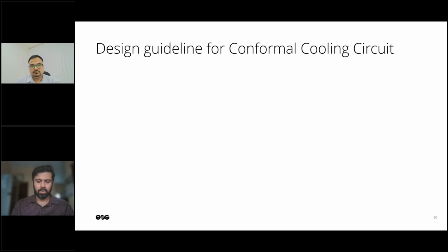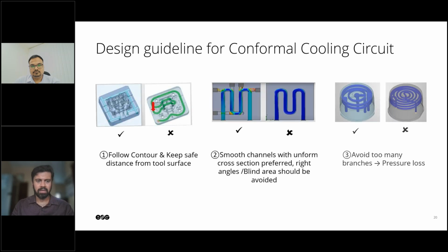So many times people ask us, what are the design guidelines for such conformal cooling circuits? So these are our three primary recommendations. Number one, take the part contour, right? Have an offset from the part contour and keep some distance. There is also a guideline depending on the material. Second is, don't have blind channels or right angles, but have smooth channels such that you have a smooth flow of the coolant. And not to have many such branches, but few branches, so that pressure losses are also minimized, right? So three major design guidelines. We can have a detailed discussion after this call or later also to see how we can help you design a conformal cooling circuit.